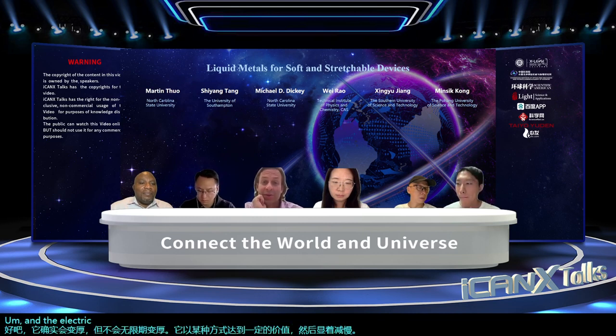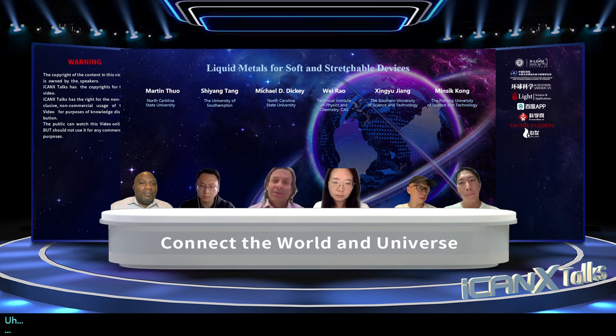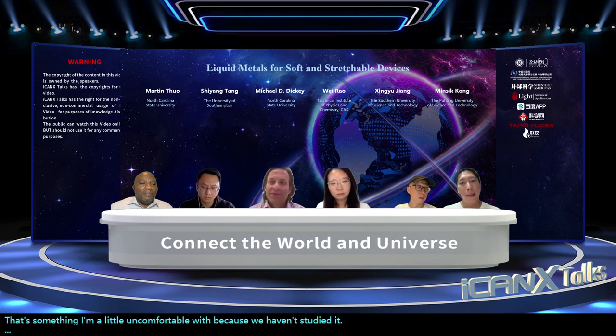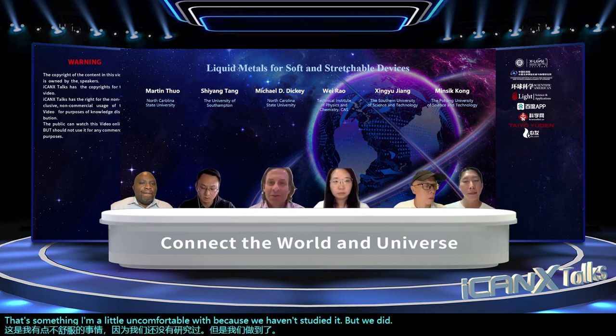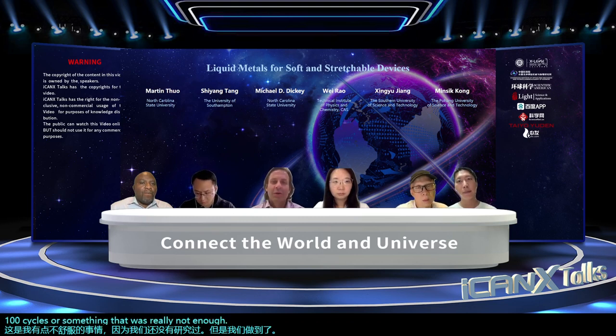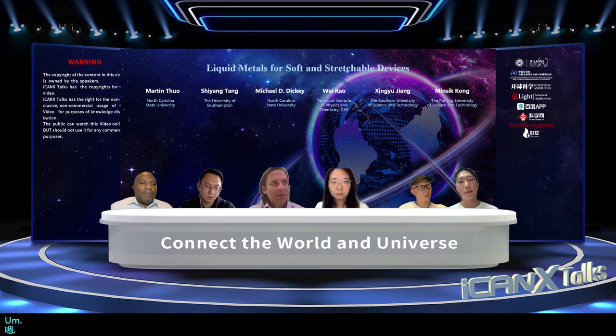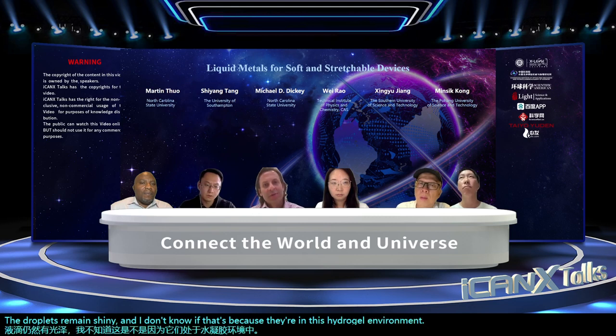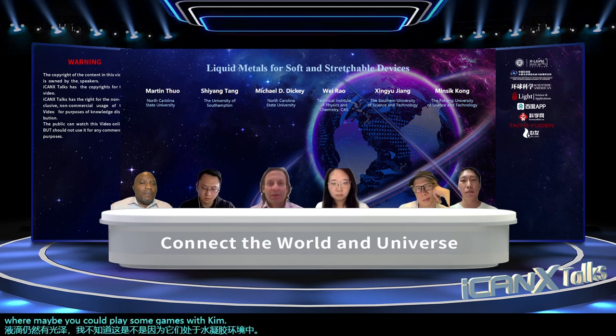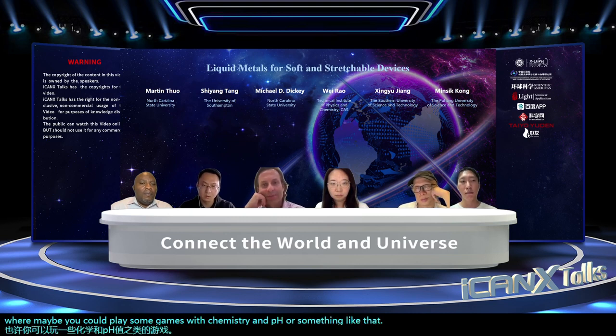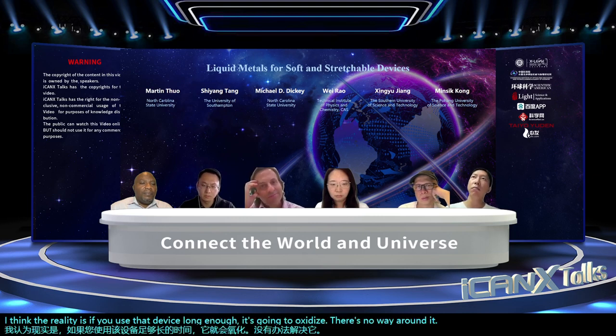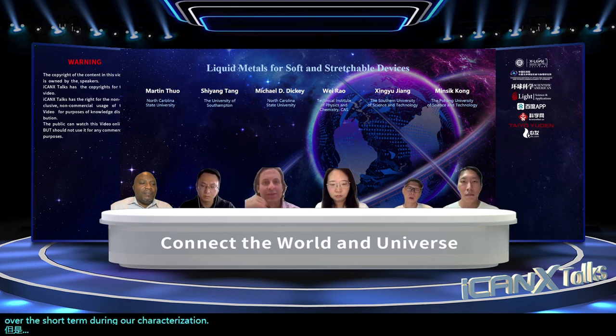And the electrical double layer harvester, that's something I'm a little uncomfortable with, because we haven't studied it. We did, I don't know, 100 cycles or something, that was really not enough, but it was a starting point. The droplets remain shiny, and I don't know if that's because they're in this hydrogel environment, where maybe you could play some games with chemistry and pH or something like that. But I think the reality is if you use that device long enough, it's going to oxidize. There's no way around it. But over the short term, during our characterization, we didn't see that being such an issue.